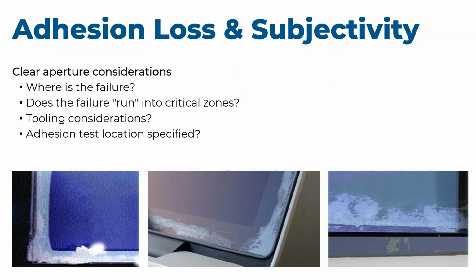Adhesion loss, some more subjectivity. Where is the adhesion loss occurring? This is an important question to ask. If you could see some of these samples I have, this is right along the edge of the part. This is extremely common. What you have to ask yourself is, where on the optic is this occurring? And is it continuing to fail? If I can get the part to fail only on the edges, and through continually tape testing it, I can't get that failure mode to continue into the critical zone, then if it's outside of the clear aperture, technically I do have an adhesion loss, but I don't know that I have a failed optic. And again, we're into the subjectivity.